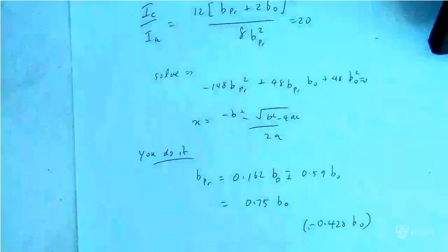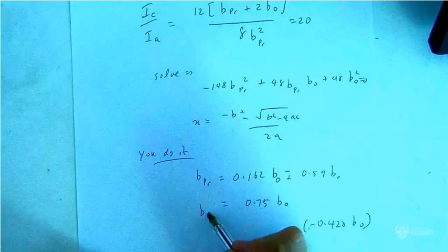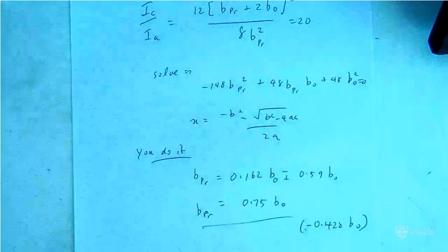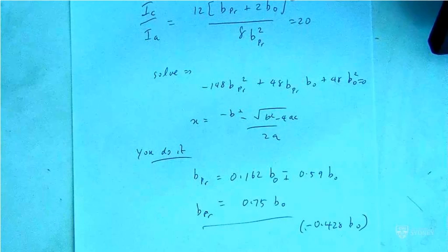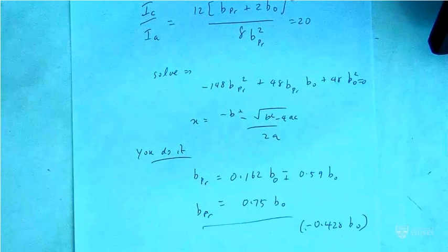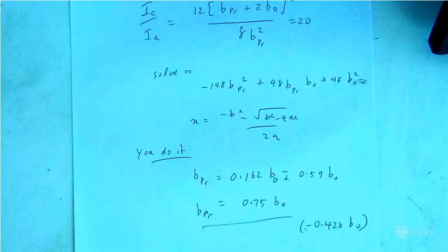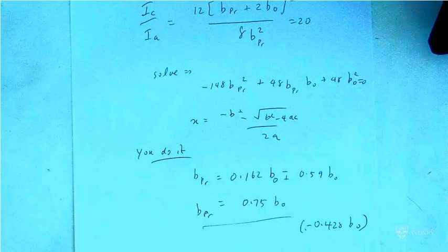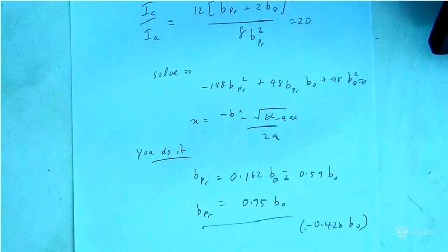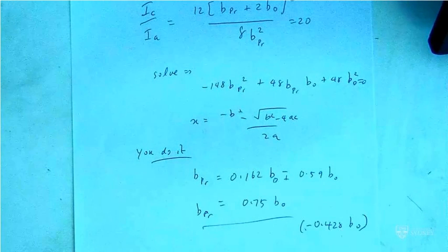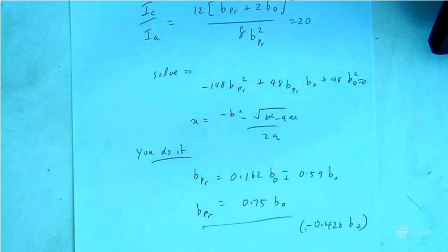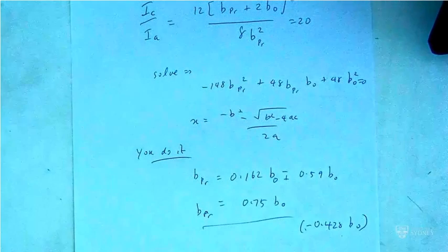So in this case, for neutrons, even though you might think the praseodymium atom is much heavier, much bigger, we can actually see that its scattering strength is 3/4 that of the oxygen atom. So from that experiment, we've been able to obtain some interesting information. First of all, the lattice constant of the material and its structure, and then some information about the scattering strength of the atoms of that material.